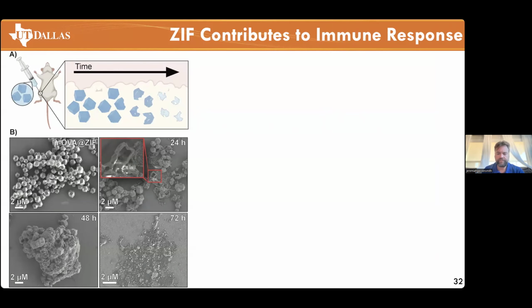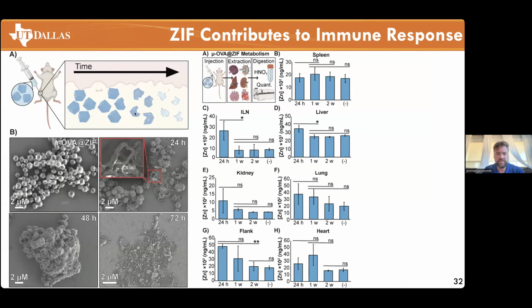And you can see what happens is the injection. So essentially what this slide shows is that if we inject it, the MOFs break down. This is just MOF injected in an animal thigh. We remove the depot after 24 hours, and you can see that essentially the metal organic framework degrades, as I told you. We also note, though, that if we look at the draining lymph node, this is panel C, we see a significant amount of zinc that's inside of that lymph node.